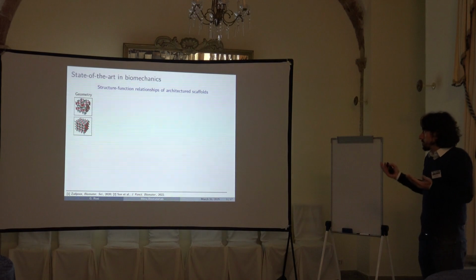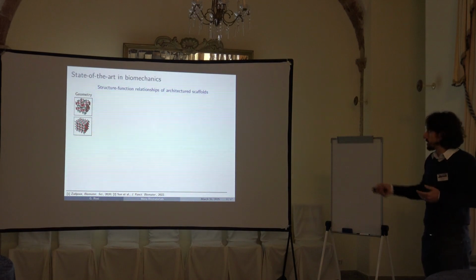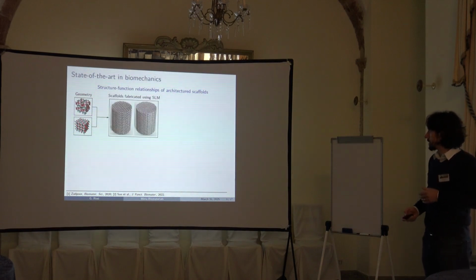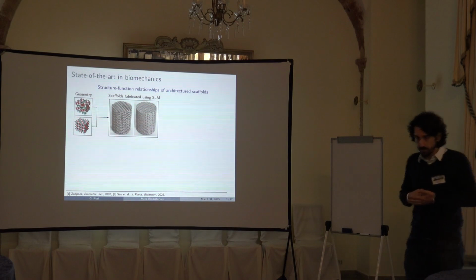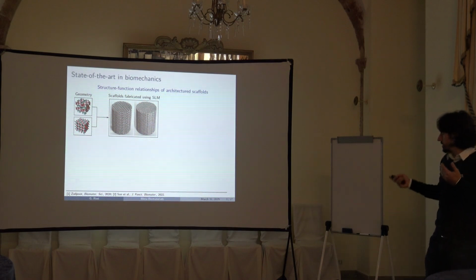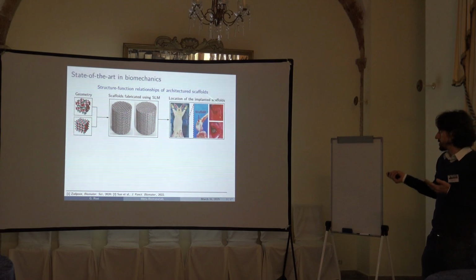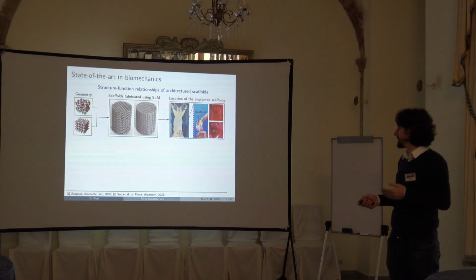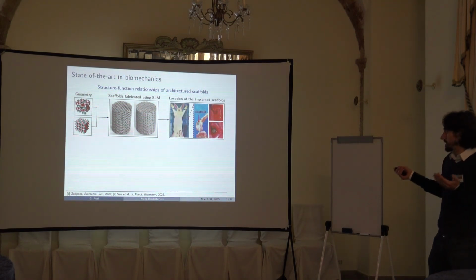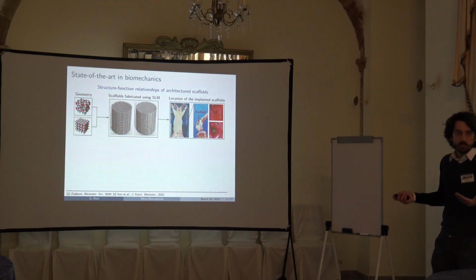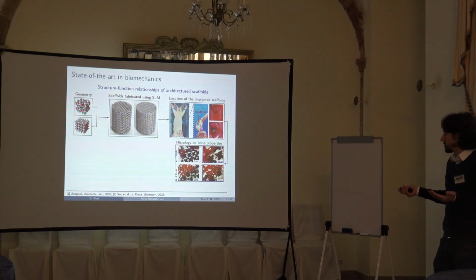Basically, in the works that can be found in literature, you choose a geometry, it can be a gyroid or something, then you build your scaffold, in titanium with laser sintering techniques, and you implant it into an animal model. Sorry for the disturbing image, but this is a needed step if you want to understand if this is really working. So the scaffold is here, and then to evaluate if it worked, you usually do histology.